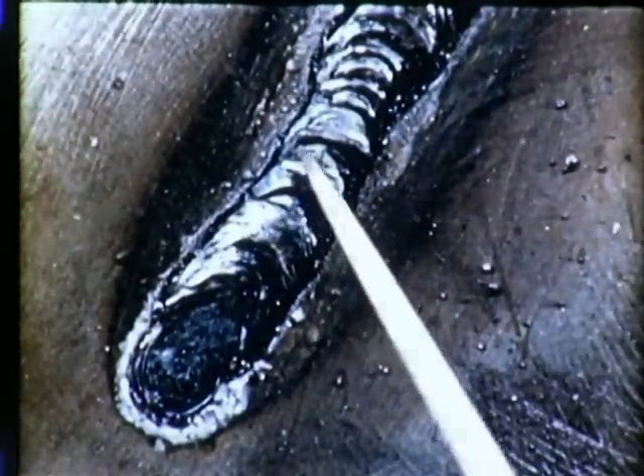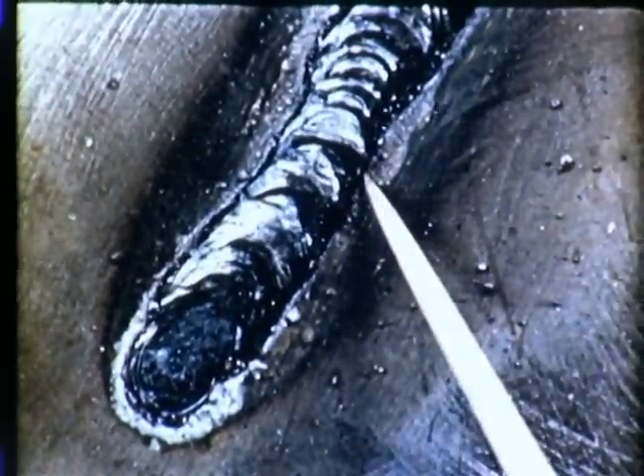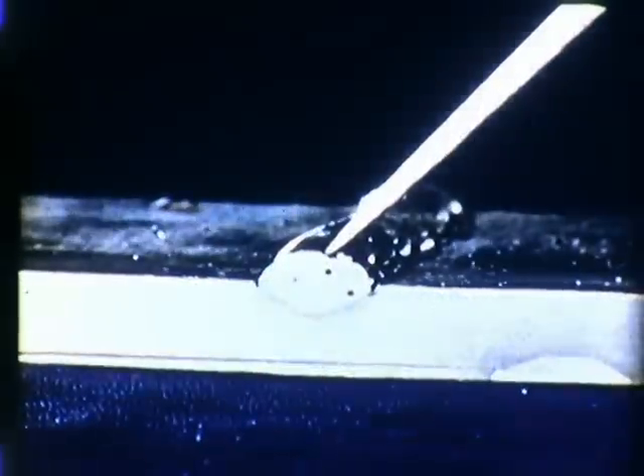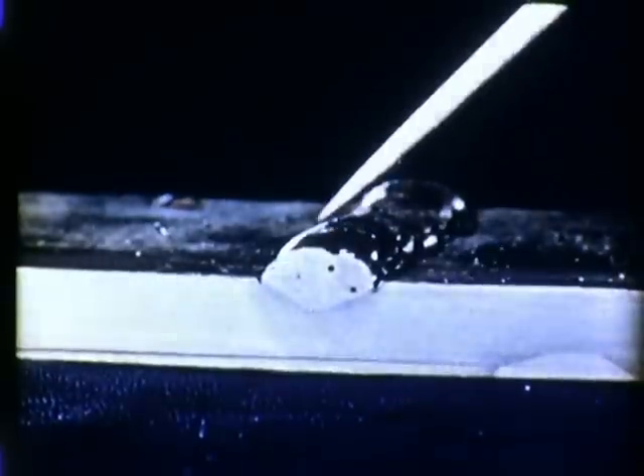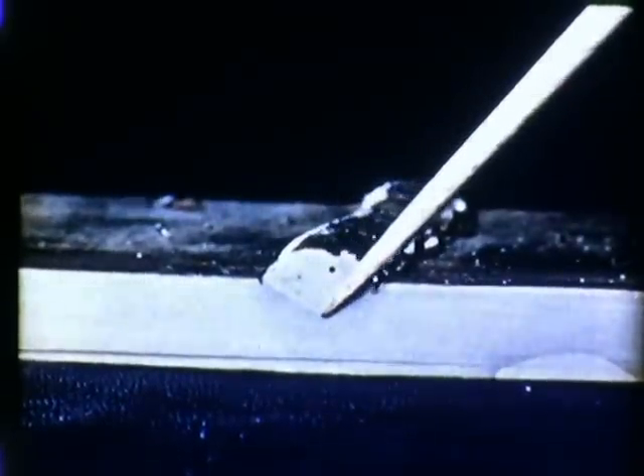If the arc is too short, a proper molten pool will not be maintained. The arc will have a tendency to short out, and the electrode will freeze to the work. The bead is uneven, with irregular ripples. It is high. There is poor fusion. Note the slag and gas pockets.